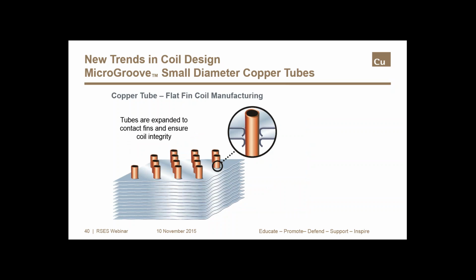When round copper tube flat fin coils are manufactured, the tubes are expanded. This fastens the tubes to the fins and also makes sure there's sufficient contact to ensure the transfer of heat from inside the tubes into the fins and finally into the air. This has been a mechanical process for many years. A rod, or what's referred to as a bullet, is physically forced through the tube.